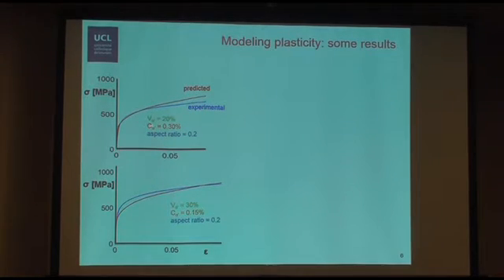Experimental curves in blue and predicted flow curves in red are superimposed to show how close we are to reality. It is for the experimental curves for two fibrous, or rather plate-like microstructure steels, and that's why I took an aspect ratio of 0.2 for the computed curves. It is each time for a certain amount of martensite volume fraction and carbon content, namely 20% of martensite and 0.30% of carbon for the first graph, and 30% of martensite, 0.15% of carbon for the second graph.